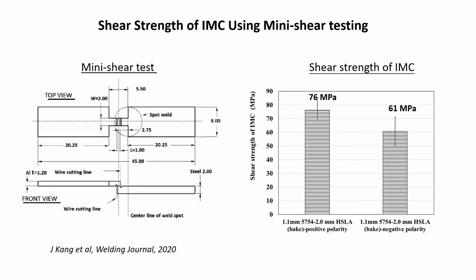After the macrostructure characterization of the intermetallic compound, we used mini-shear specimens to test the strength of the intermetallic layer formed at the interface of the aluminum to steel welds. The shear strength of the two kinds of stack-ups is higher than 60 MPa, which is dominated by the intermetallic compound layer thickness of the weld nugget periphery. Here the error bars represent one standard deviation.